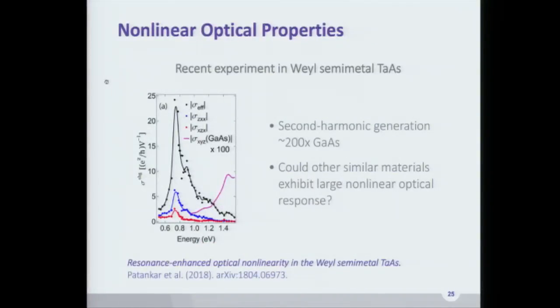I keep mentioning these materials also have interesting optical properties. So this is linking the fact that I love thinking about the photon as well as thinking about hydrodynamics. The same materials actually have very, very high Chi2, right? So they're very low symmetry. And you think about the fact that gallium arsenide has been thought about as an interesting material with nonlinearities, and tantalum arsenide and the whole family of Weyl semimetals that follow tantalum arsenide could have similarly very high Chi2. Of course, you'd want high Chi2 at the same time as low loss, which is non-trivial. But again, we're looking at this class of materials to see if the optical nonlinearities in these Weyl semimetals could tell us also something about the physics in these materials.